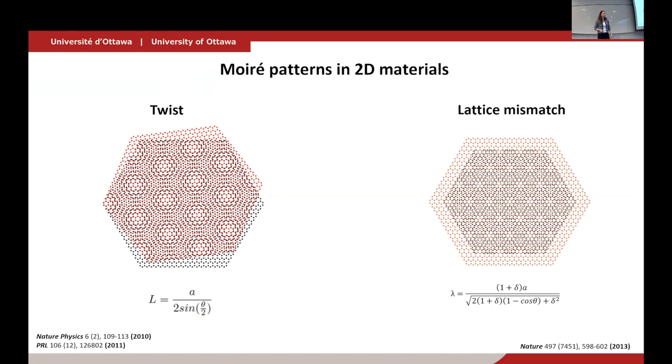In the context of 2D materials, if you superpose one layer of 2D material on another with a small twist, you get an interference pattern. The electronic properties depend on the type of atoms and the periodicity of the lattice — adding another periodicity via the moiré means something must happen to the band structure. Similarly, if you have two layers that are simply lattice-mismatched without a twist, you get a moiré pattern that will change the properties. With the entire family of 2D materials available to twist or mismatch, there's a whole zoo of materials whose properties we don't yet understand.